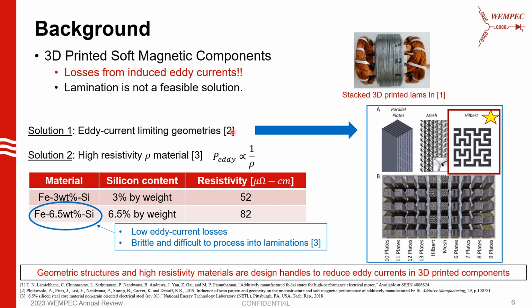So reference 2 from Oak Ridge National Labs proposed different microstructures to emulate laminations, characterized them using conventional material characterization tests on miniature samples, and reported that using the Hilbert pattern can reduce the eddy current losses significantly in 3D printed components. The Hilbert pattern is also attractive since it is a continuous pattern and it lends itself very well to 3D printing. There is no literature where the Hilbert pattern is adapted into a full stator or a full electric machine component. The other solution we found in literature was to use high resistivity materials such as 6.5% silicon steel.